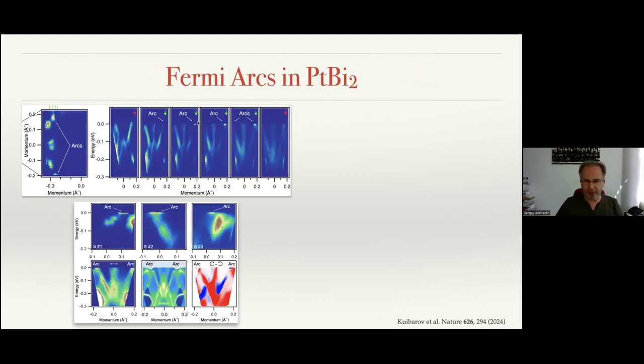But we have never seen these kind of features in angle-resolved photoemission spectra. And it turned out that nobody has seen such sharp and strong features in angle-resolved photoemission from solids, one could safely say that. So it turned out that these small portions of the map are arcs, which we first detect with that. We saw that they are very flat. They're sitting very close to the Fermi level. And again, exactly in the places where the theory predicts them to be.